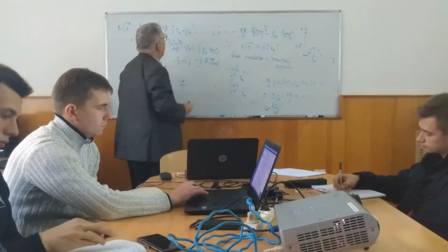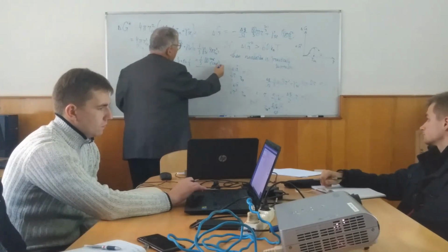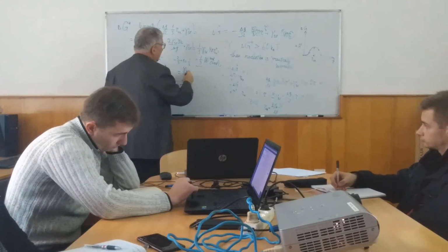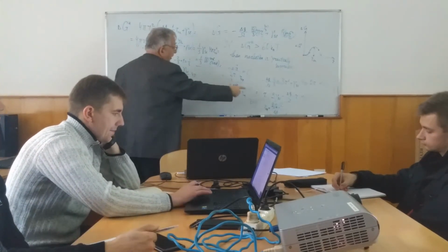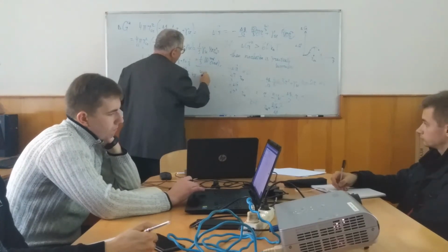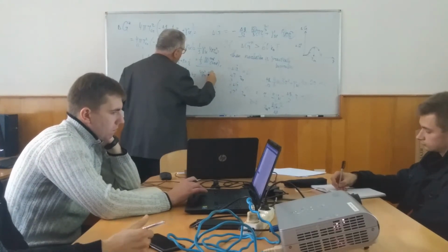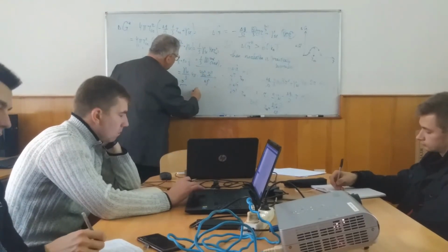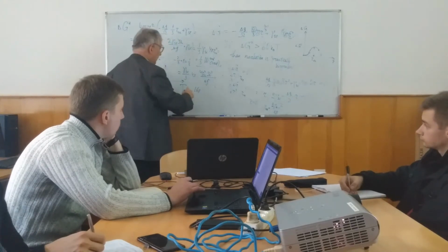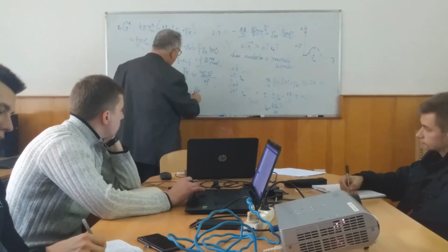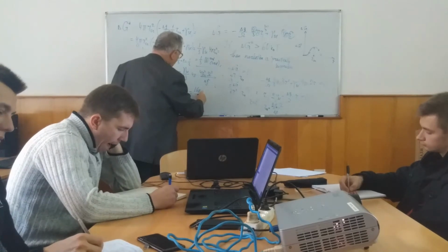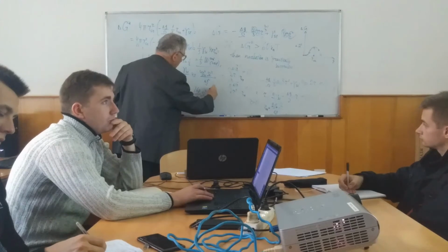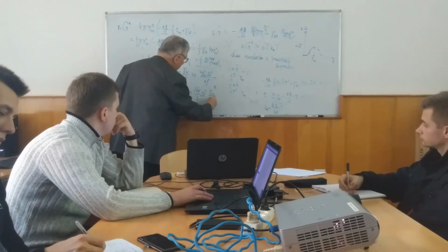Okay. Now, if we substitute this, we obtain gamma SL divided by 3, 4 pi, this 4 gamma SL squared omega squared divided by delta G squared. So it means 16 pi divided by 3 omega squared multiplied by gamma SL cubed divided by delta G squared.